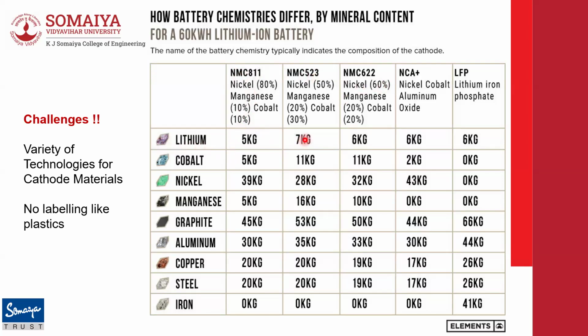Now, if you look at the total amount, lithium is only 5 kgs. Cobalt, as you can see, I'm avoiding cobalt in LFP, and that is one of the reasons that LFP actually came into the picture. Nickel also is avoided over here. Now, this LFP technology is something that perhaps Indonesia would be adopting with a pinch of salt, because the technology is cost effective. However, it also does not ensure the use of one of your largest resources. But it's sort of a double-edged sword that you have over there. Manganese also is another element that is in the NMC, because the center is basically manganese. Graphite is one of the single most abundant elements in a battery.